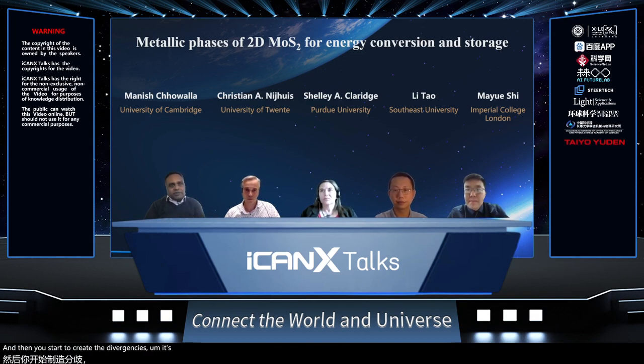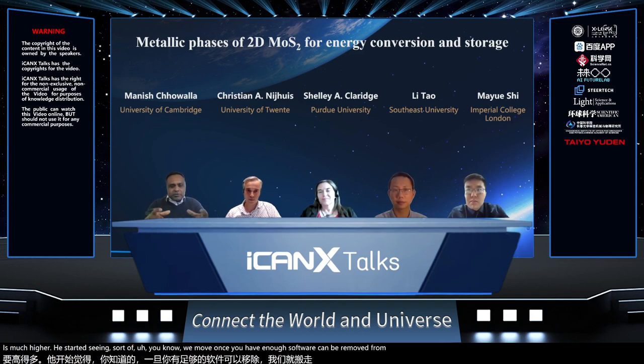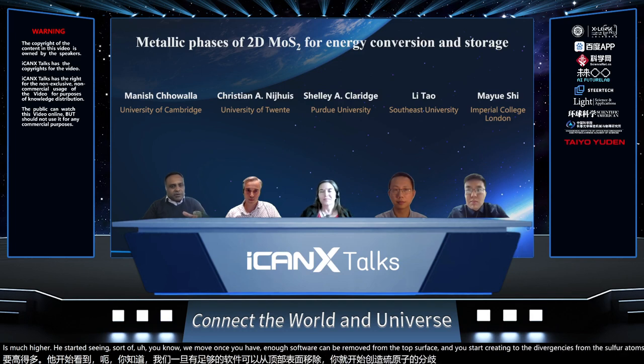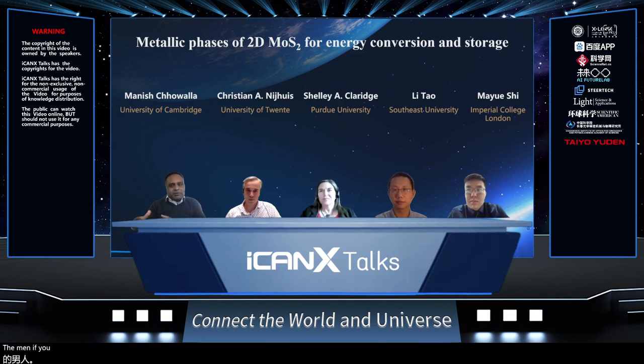It's interesting because we found that the requirement for removing molybdenum is much higher. Once you have enough sulfur vacancies removed from the top surface, then you start creating di-vacancies from the sulfur atoms below. And then if you go to very high helium ion dosages, then you start to remove the molybdenum as well, destroying the framework of the MoS2.